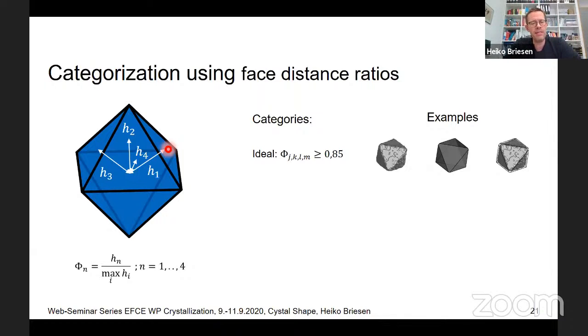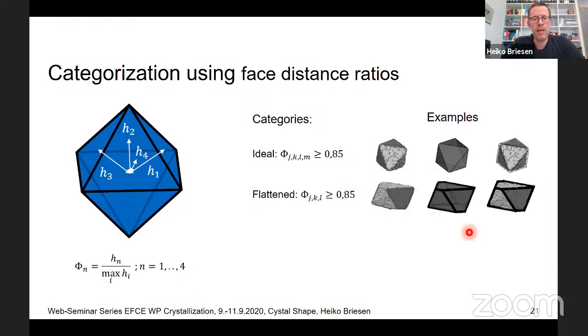So we considered ideal, this is an arbitrary threshold which we chose here, a value of 0.85. If each and every one of these values, this means phi k, j, l, and m, all 4 of them, are larger than 0.85, then we end up with crystals like this, which are pretty much ideal, I would say. If only 3 of them have a large value and one of them is smaller, you basically squeeze the crystal somehow to get this type of flattened crystals here. So only 3 of these values are larger than 0.85.